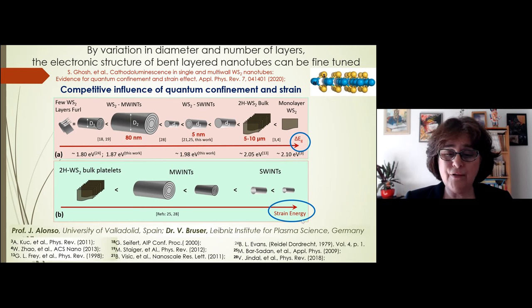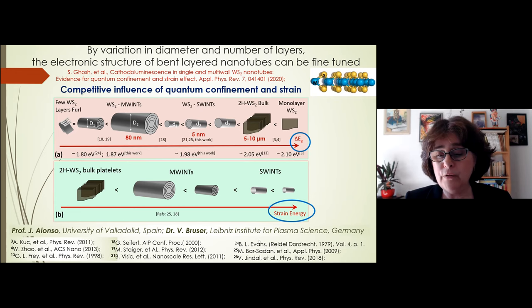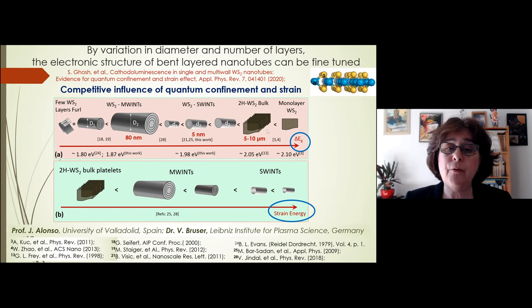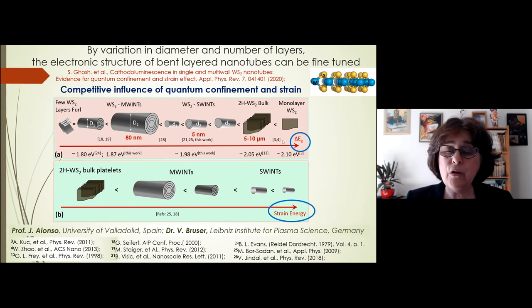The last topic is the electrical conduction of individual nanotubes under tensile stress, published two years ago in collaboration with Professor Antonio Bartolomeo from the University of Salerno. Using two tungsten conducting probes, individual nanotubes were caught. Initially, nanotubes were held by van der Waals forces between the nanotube and the probe tip, but later the contacts were strengthened using an electron beam. Carbonaceous material in the microscope atmosphere acted as a glue at the contact, allowing the nanotubes to be stretched.